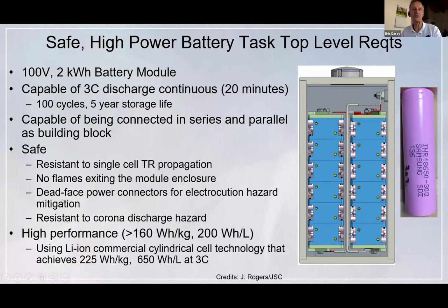We want to be resistant to a single cell going into thermal runaway because that's the one failure mode that we can't put a fuse on or put a positive control on. Even though they're rare, occurring at about a 1 in a million probability from manufacturers that have their processes under control, every once in a while even a reputable manufacturer will make a bad lot. So we need to be prepared for that. Plus, we also have a requirement that no flames exit the battery enclosure in our spacecraft. And when we get to high voltage, we also have to have dead-facing of our connectors for electrocution hazard control. And then we also have a corona discharge hazard when we get to low pressures at high altitude.